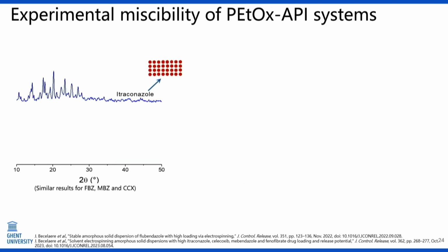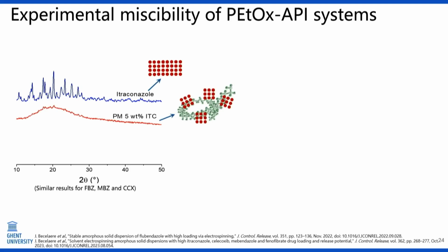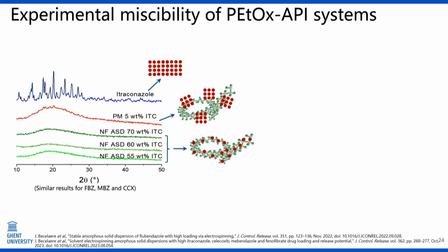A theoretical prediction that we, of course, studied by experiment. And then we used XRD. Here, this is an XRD of a pure drug. So we see the crystalline peaks of the crystalline drug. If we only add a little bit of that crystalline drug, just by physical mixture, to a PEtOx, then we see the amorphous big band with the crystalline peaks. So we can already pick up small amounts of crystalline drug in there. And then if we look at our electrospun amorphous solid dispersions, we don't pick up any crystalline peaks, even at weight percentages of 70% of drug, so proving that we've indeed an amorphous solid dispersion and we don't have crystallites in there.